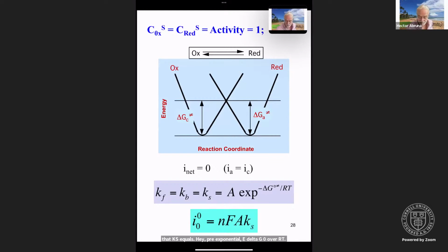So this is what we had before, a little bit more explained. So we're looking at Ox going to Red, assuming activity equals 1, and we're at the standard potential. Again, net current equals 0, meaning the anodic and the cathodic currents are equal and the same, except they have different signs. Under this condition, k forward equals k back, because you're at equilibrium, equals ks, the heterogeneous charge transfer rate constant, pre-exponential e to the minus activation energy over RT. And so then we can solve for the standard exchange current density as nFAks.